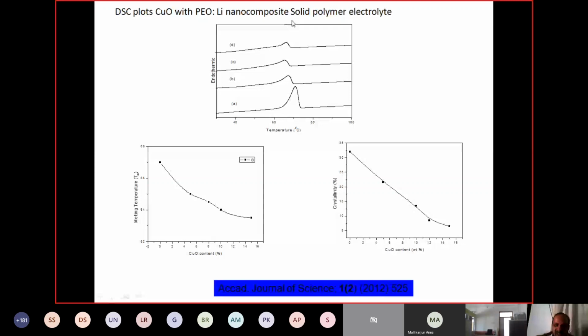So this study is about the thermal stability of the material. You see here, when we dope CuO particle into PEO-LiClO4, the thermal stability also increased. PEO-LiClO4 thermal stability is only up to 325 degrees. But when we dope the CuO nanoparticle into that, the thermal stability is above 400. That means when we added the nanoparticle, the thermal stability is increasing.